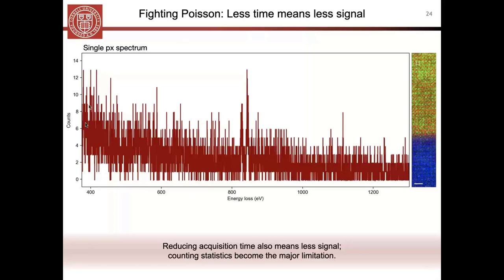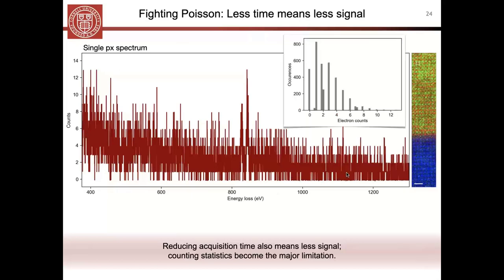But the other thing you'll notice, especially if you take a statistical distribution of the counts in this spectrum, which is what this plot shows up here, is that we're really sitting in a Poissonian regime. And so if your counts are on the order of 1,000 or 10,000, then you have noise, of course, but you have a Gaussian distribution of noise. Here, because we're so signal limited by just how fast we have to run our experiment, we're sitting instead in a Poisson regime. And so when you're down here, the root n and n comparison between your noise and your signal start to be very comparable when your n is on the order of four, right?